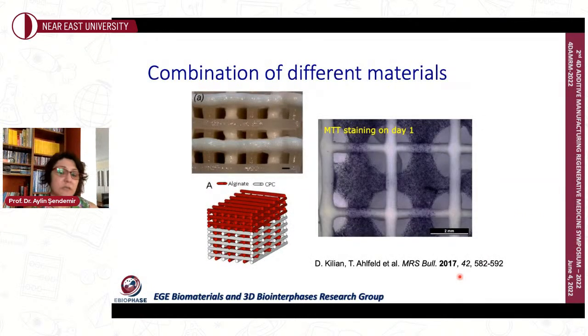So a very common technique that is applied also in our laboratory too is combination of different materials. Because of all those requirements, keeping cell viability plus the structural integrity is not very easy to accomplish with a single material. Usually hydrogels are good in keeping cells viable, but mechanically they are not strong. Therefore, using different materials, for example, in this example, there is the calcium phosphate in some layers that is keeping the structural integrity of the material, but other layers being printed by hydrogels that are keeping the cells alive.